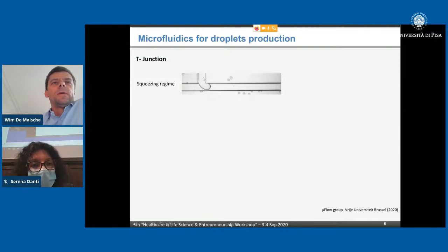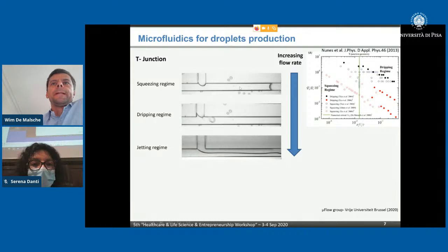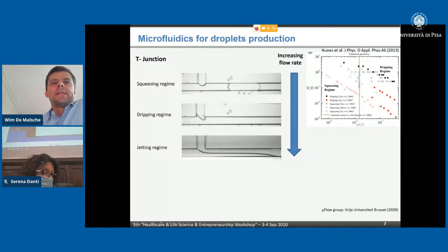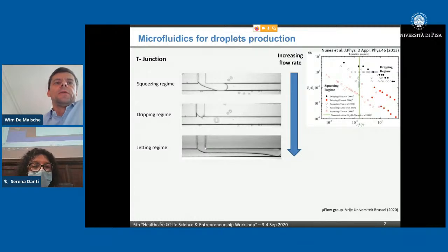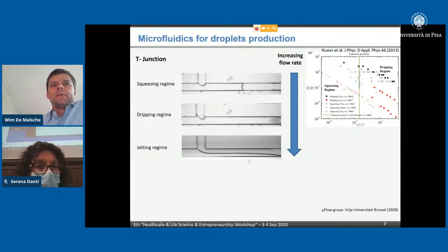So making droplets, when we look at an individual channel, can first of all be done in a simple T-junction. If the flow rate is relatively low, you make drop by drop, they touch the wall here, and you're in the so-called squeezing regime. As you increase the flow rate, you get first to the dripping regime, where you're not touching anymore. The velocity is increasing, and so the droplets are pinched off earlier. Then you move into a so-called jetting regime, where this unstable blob of liquid will decompose. But the problem with the last case is that you will not have monodispersed droplets, so you will typically avoid going into this region.